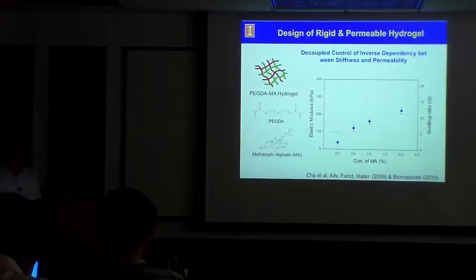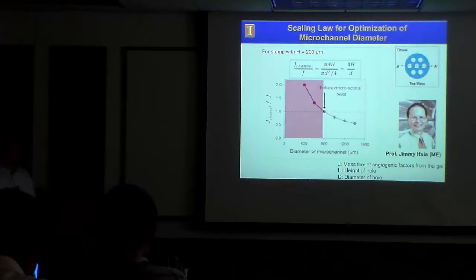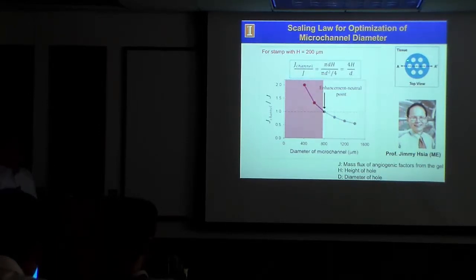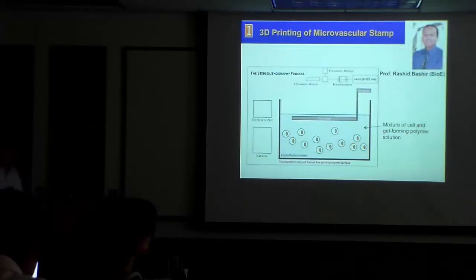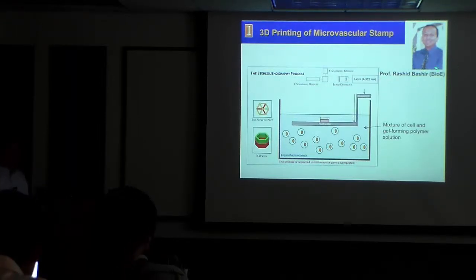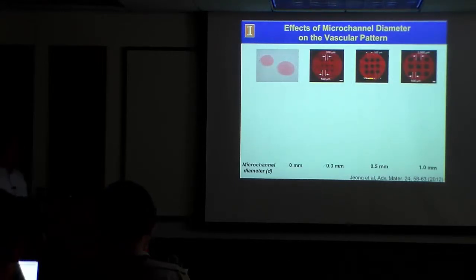To make this hydrogel with controlled microchannel size, we used the decoupled control technique and optimized microchannel dimensions through computational simulation in collaboration with a professor in mechanical engineering. Using a simple equation relating molecular flux to microchannel geometry, we found that a microchannel diameter around 700 micrometers is optimal to achieve protein localization, especially for hydrogel with thickness around 200 micrometers.